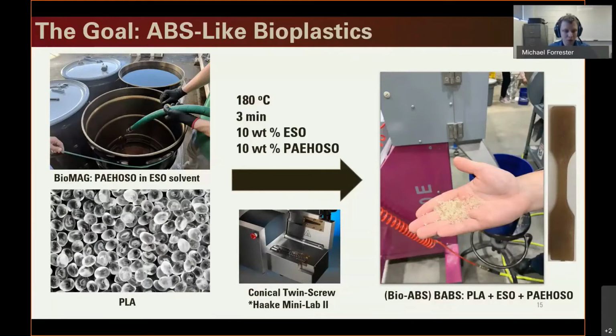And so what we did is we took our PLA and we took our Biomag that we talked about earlier. We compounded them in the mini lab, and then did some injection molding to make some nice tensile specimens and Izod specimens.